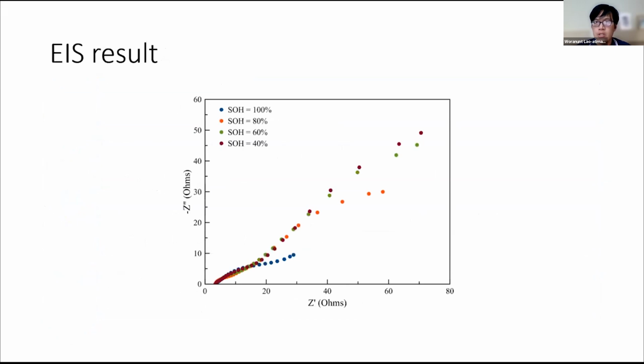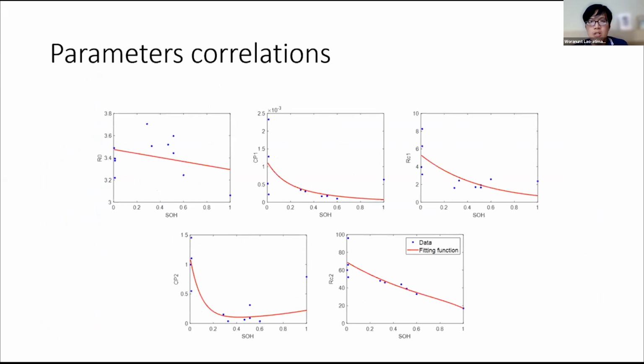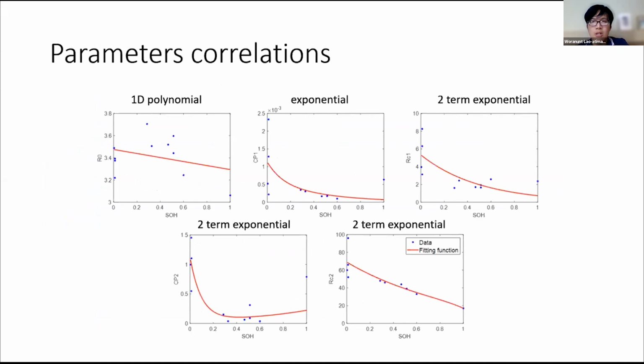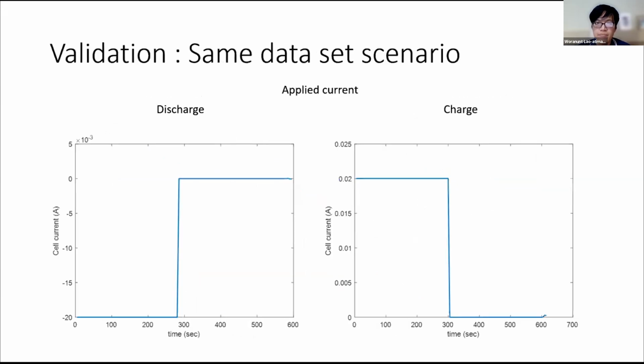For the EIS test as shown in the slide, when the cycling test is going on, state of health decreases and the impedance increases instead. The equivalent circuit model parameters extracted from the EIS test were fit into the correlations as shown in this slide. The functions used to fit the correlations were the polynomial function and the exponential function. For validation, at first, it was validated with the same data that was used to create the model. The plot shown in the slide is the applied current profile, with the discharge and charge profiles separated.